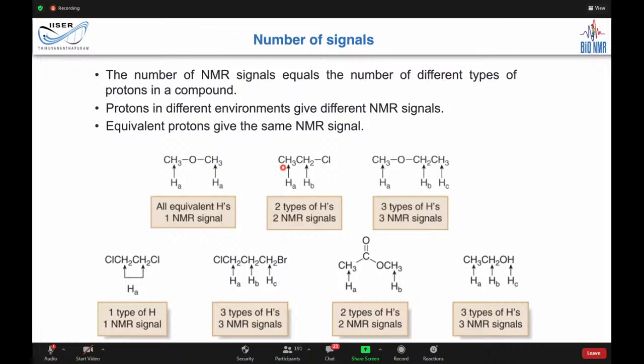While for this molecule, the CH3 and the CH2 will have two different signals, because this CH2 is directly attached to a chlorine and this CH3 is not. So the chemical environment around here is going to be definitely different from CH2. So if the hydrogens are in different chemical environments, then they will give you different signals. That's the whole point. Here again, if you have CH2, CH2, highly symmetric, both of them have the same chemical environment, so you have the same signal. But if the Cl was replaced with bromine, then there is an asymmetry. So this and this hydrogen will have different chemical shifts.